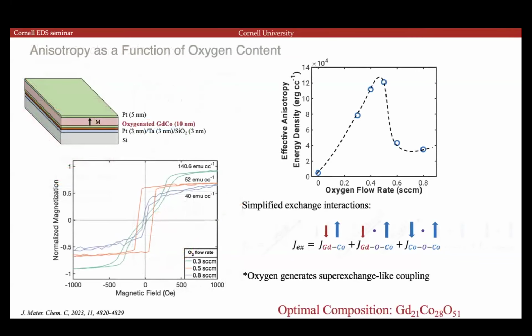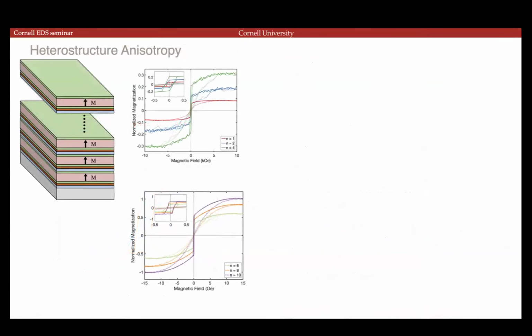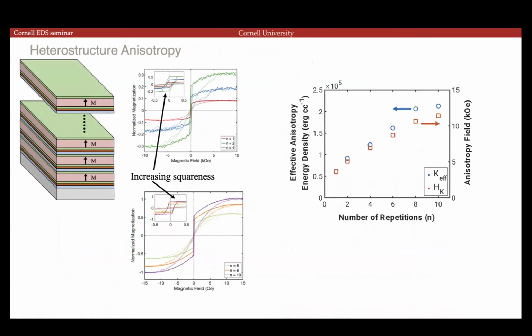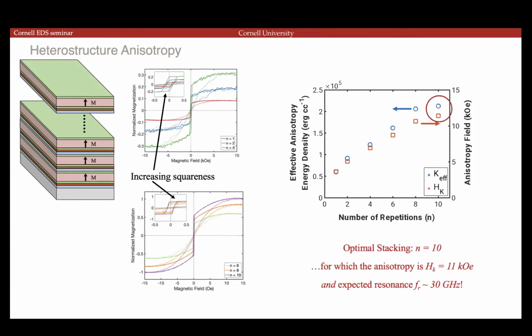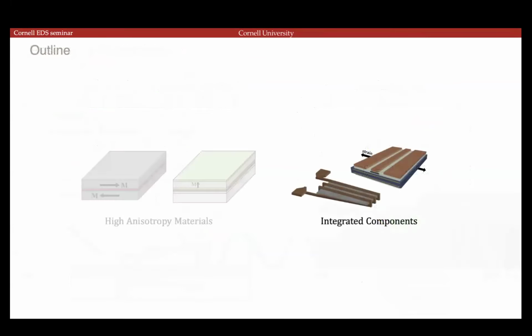So with all of this, if the majority of the film is oxidized, we can get a huge increase in the effective anisotropy. I think I'll finish this up and end here. So then we can stack the films on top of each other and increase the anisotropy further. With 10 layers of this stack, you get an anisotropy field of about 11 kiloersteds, which corresponds to a resonance frequency of 30 gigahertz. With that, we are also working on integrated components, which would be tunable.